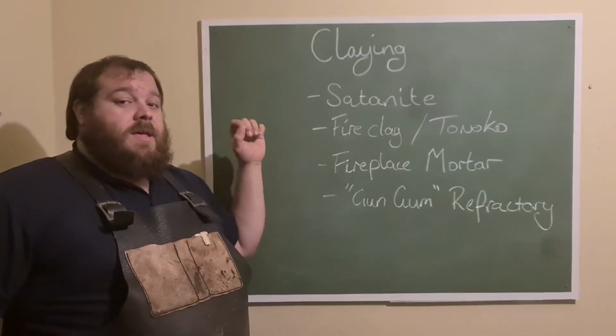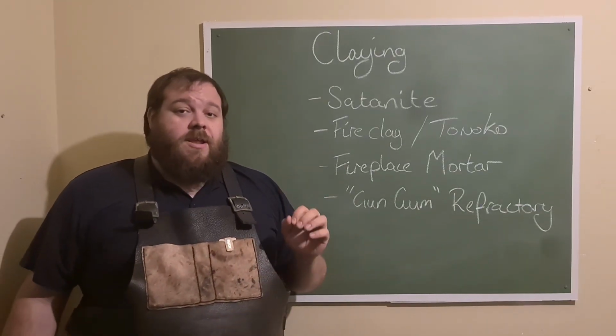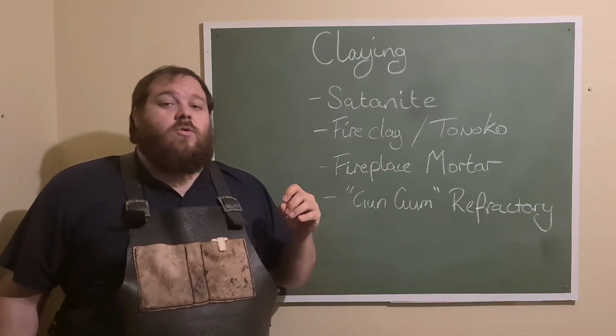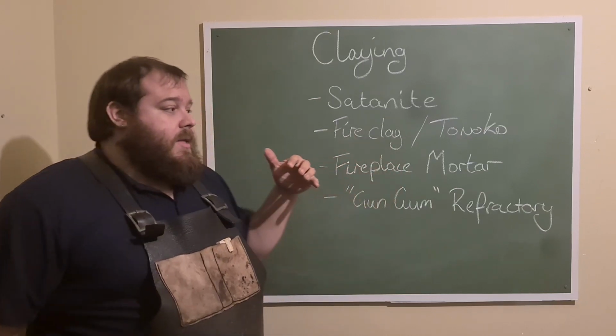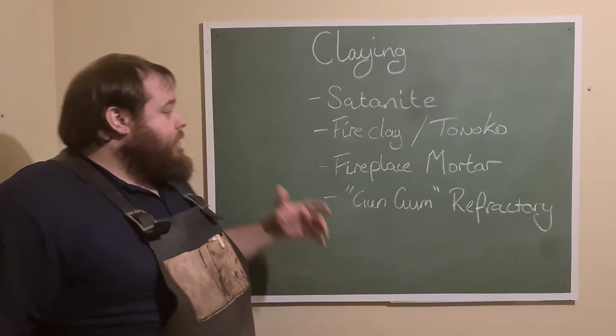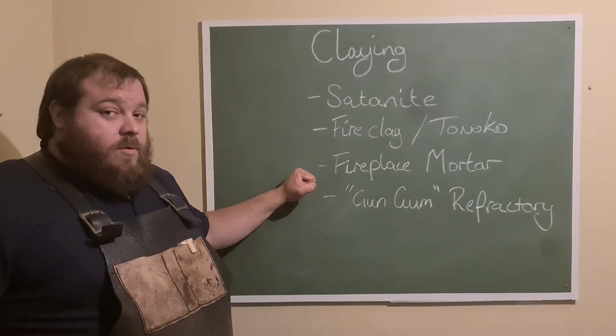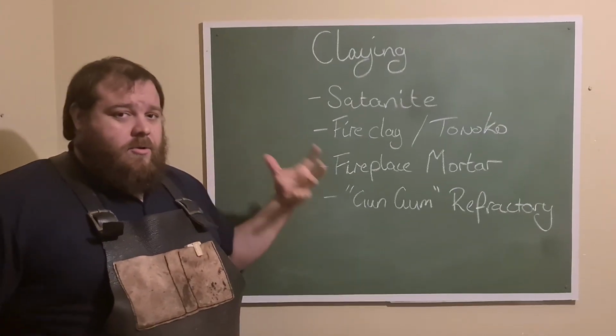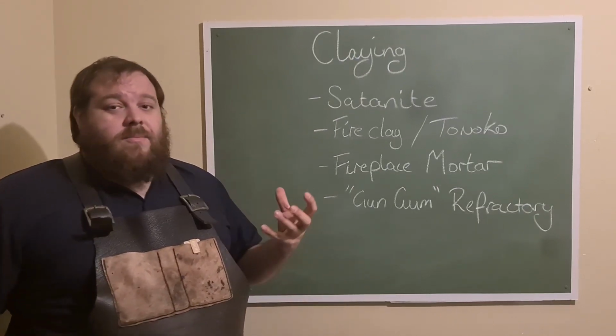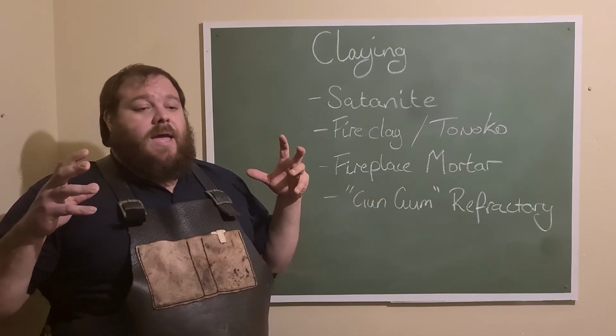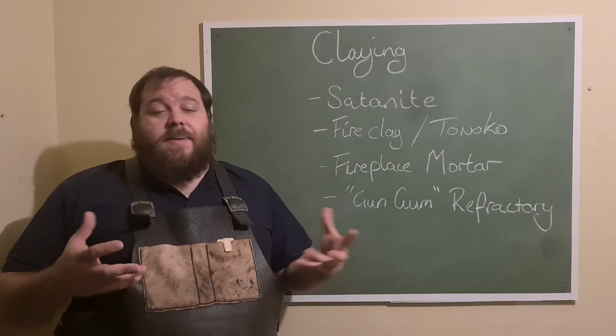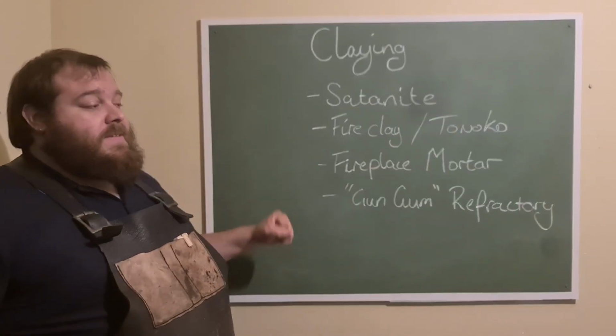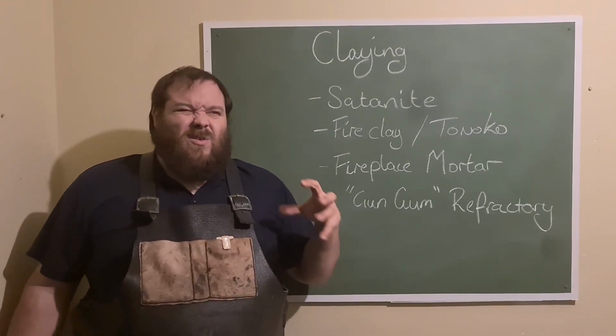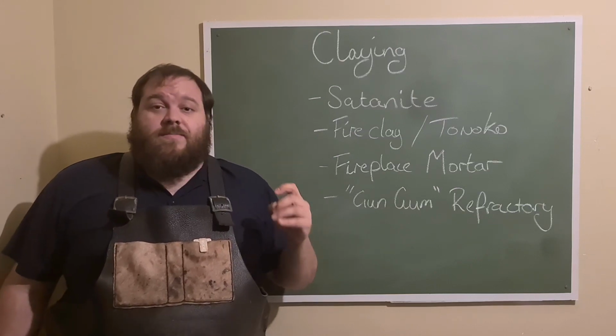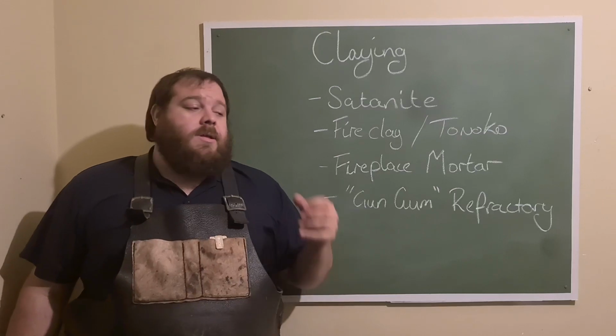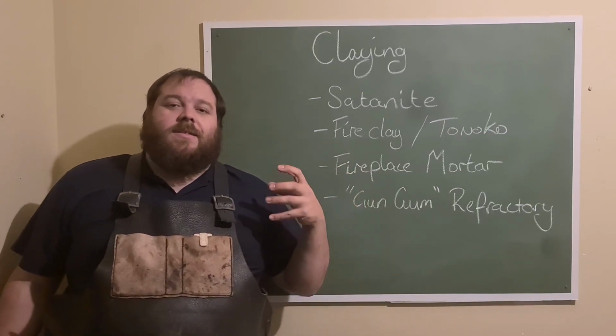But for the best results, you should mix one part charcoal, like really finely ground charcoal, to four parts of your clay in order to increase the thermal efficiency of the clay. Because we're using it in this format and not making pottery out of it, obviously. I have also used things like fireplace mortar. There is a local equivalent in our local hardware stores, which is Lanco 156, which is just a brick and mortar for making fireplaces, and putting together fire bricks to make brick ovens, like pizza ovens. And the last one that I have seen used but haven't used myself is things like gun gum, which is normally a sort of refractory sludge mixed with fibrous material, normally a ceramic fiber like Kaowool. And that is probably my least favorite because it has the ceramic fibers in it.